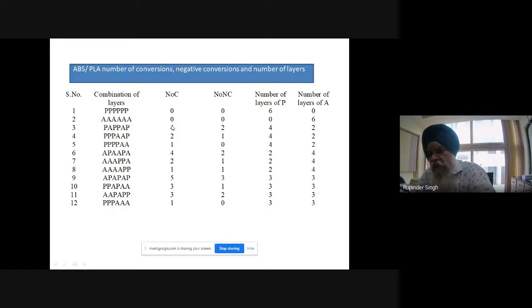Then what is a negative conversion? Negative conversion means I am depositing the ABS first and putting the PLA over it, right? So what will happen? The PLA will have a side flow because of the difference in the glass transition temperature of the materials. If the ABS is at the bottom followed by the PLA, there will be a side flow of the material. We are calling it a negative conversion, right? So in this case, you see P to A is non-negative, A to P is one negative, then here again A to P is two negative. So there are two negative conversions. Then how many P's are there? 1, 2, 3, 4 P's. And how many A's? 2 A's.